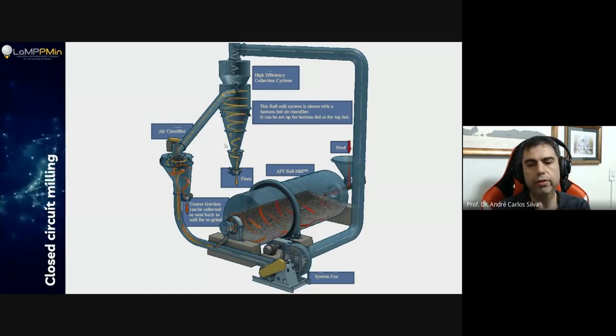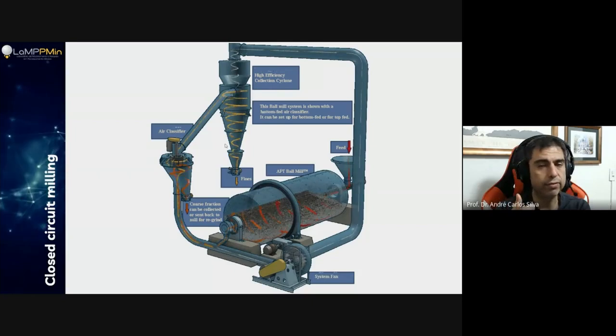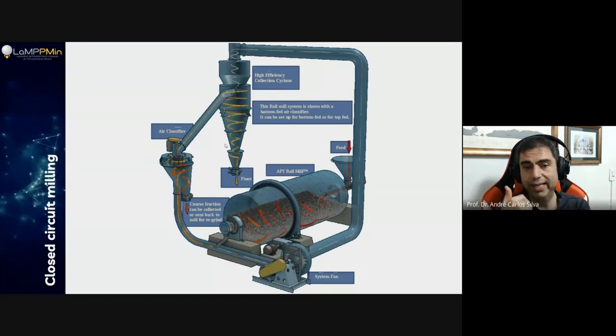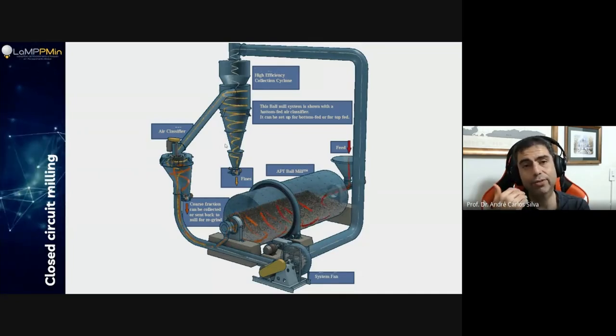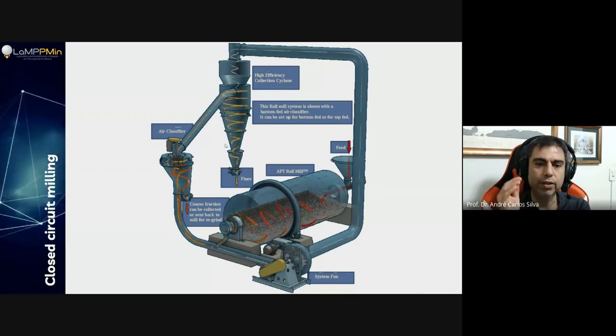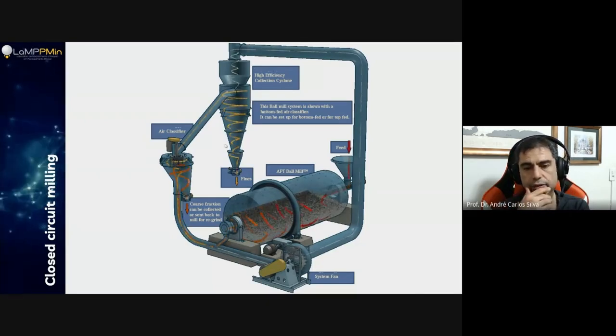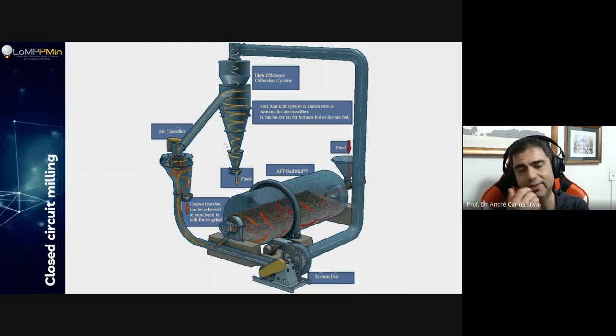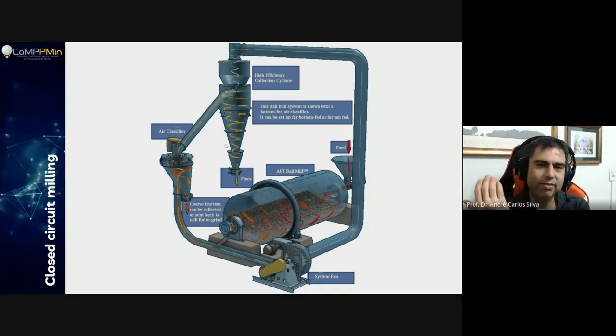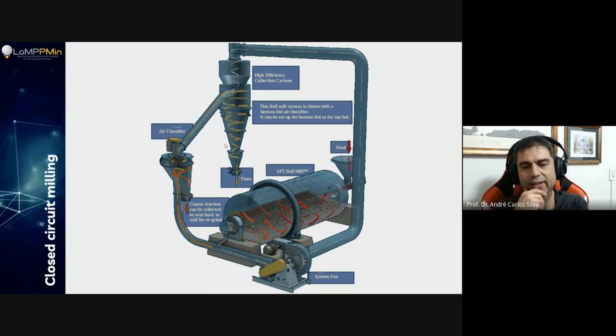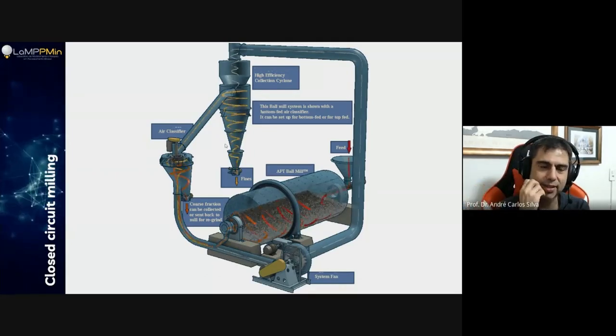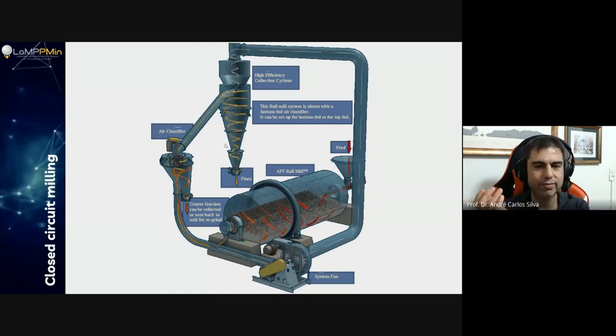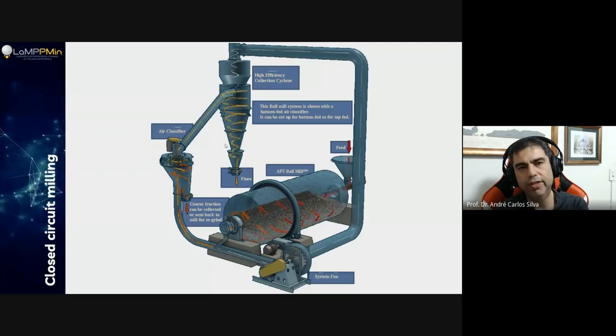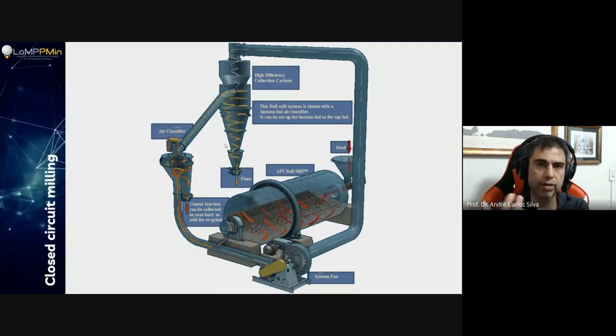And on the other hand, you use water in order to remove heat from your system. If you don't put water, your mill can go up to like 80 degrees Celsius or even more. And when we stop the mill and we go inside of it just to change the liners of the mill, some mills are just laying around in the sun, okay? And then you can reach like 50 or 60 degrees Celsius inside of the mill, because you don't have any window. It's a very narrow area, and it's all made of steel. So yes, in a place like Catalão where you can easily reach 40 degrees Celsius, the mill is going to be like 20 up to 40 degrees higher than the surrounding environment, okay?